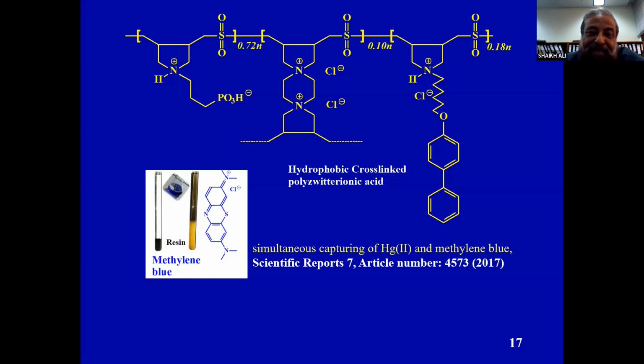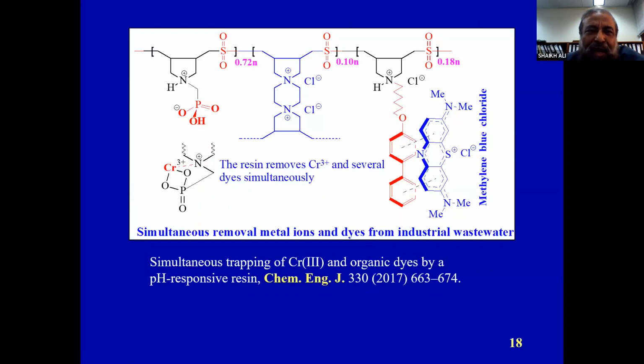But if you want to recycle it, then decrease the pH, and decreasing the pH will make it all cationic, and that will repel the methylene blue. And then I can show you another one here that is capable of removing chromium, and at the same time it can remove methylene blue with the help of this hydrophobic pendant that can interact with the methylene blue, and chromium with this chelating moiety of aminophosphonate.